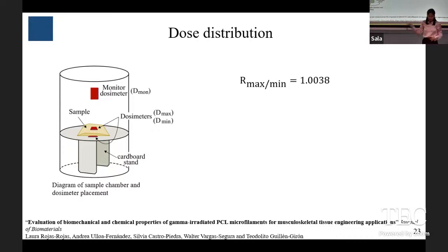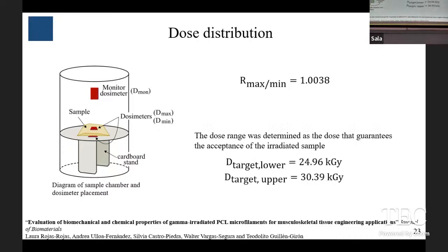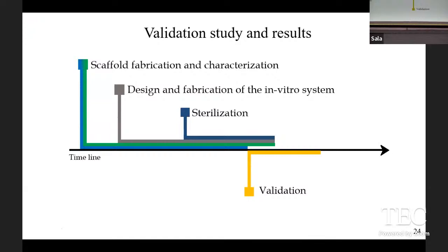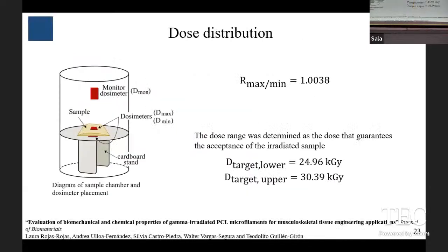So for that, we did a dose distribution study in which we calculated the uniformity coefficient, which is the first line. If the uniformity coefficient is very close to 1, it means that the dose is uniform within the sample chamber. So that means that we can place several samples inside the sample chamber and they all will be receiving the same amount of gamma rays. And also we calculated the range of dose with the uncertainty. And as you can see, 25 kilograys, the one that we want to use, is right between the lower and upper values.